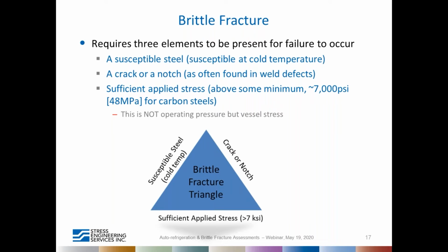Usually the code varies, as you look through the codes, the number varies from 6 KSI through 8 KSI, which is actually considered the primary stress that would cause a brittle fracture. So if you operate below that stress, then you're not closing this side of the triangle, because typically the presence of a crack or notch is always considered as present. The susceptible steel, this is where the material behavior comes into the picture, whether the material behaves brittle or ductile. We'll go into that in a little bit.